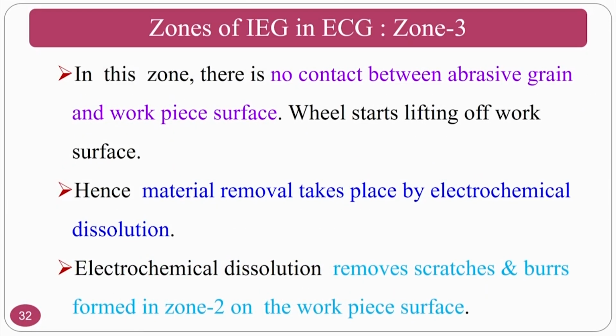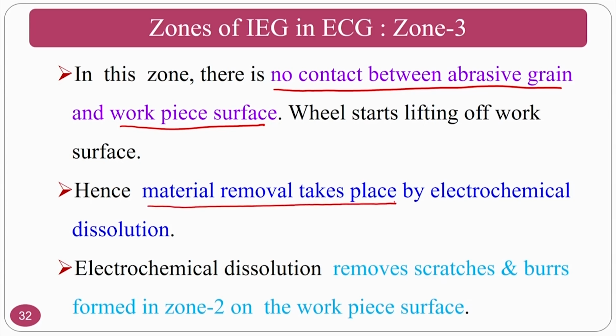In the third zone, what is going to take place is there is no contact between the abrasive grains and the workpiece surface. That means that your material removal is completely again by virtue of electrochemical dissolution. Okay. So, the entire material removal takes place by electrochemical dissolution. Electrochemical dissolution removes the scratches and burrs formed on zone 2 of this workpiece. That is the beauty of this particular process, that whatever burrs and scratches are formed during the abrasion action of zone 2 also will be electrochemically dissolved.